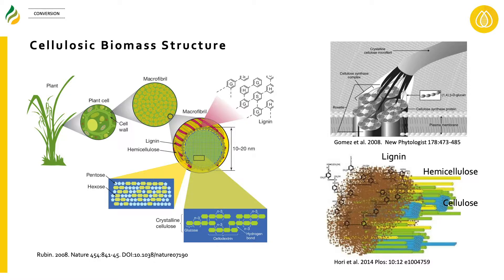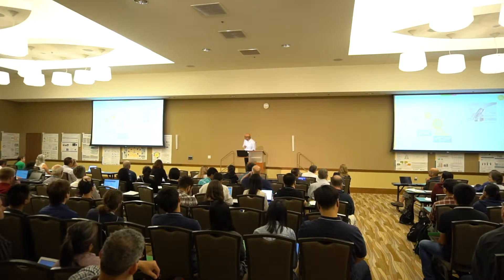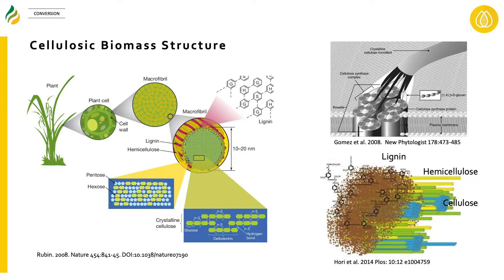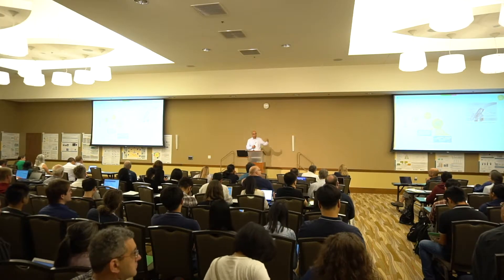If you look at the structure of the biomass, we see that the cell wall is made up of a very complicated structure of cellulose, hemicellulose, and lignin. Cellulose bundles are made up of braided fibers that are perfectly aligned at a molecular level and give this very crystalline structure — also called microfibrils. Surrounding the microfibrils is hemicellulose, a C5 polymer cross-linked with cellulose, made up mostly of xylose, arabinose, and galactose, along with C6 sugars. Lignin is a highly branched polyphenolic structure that fills spaces between cellulose and hemicellulose, providing mechanical strength to the cell wall.